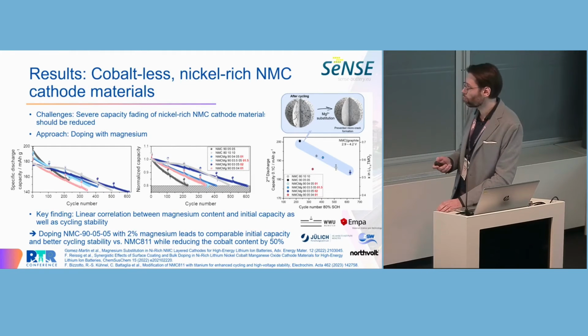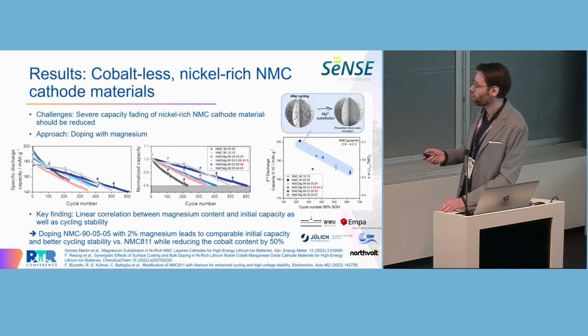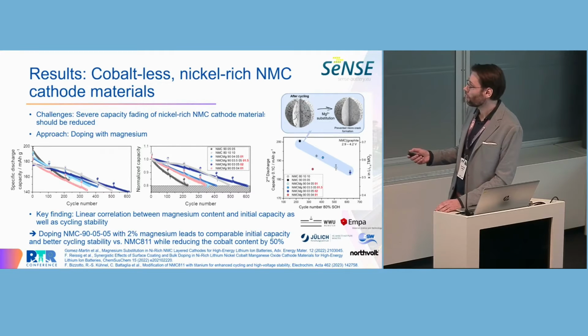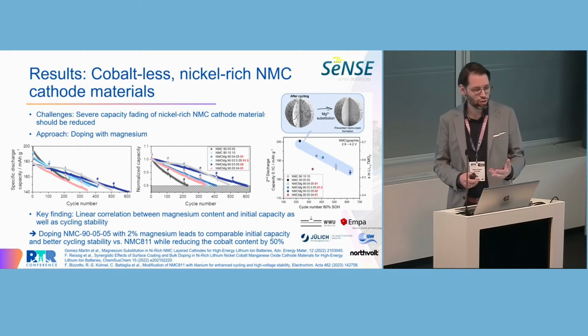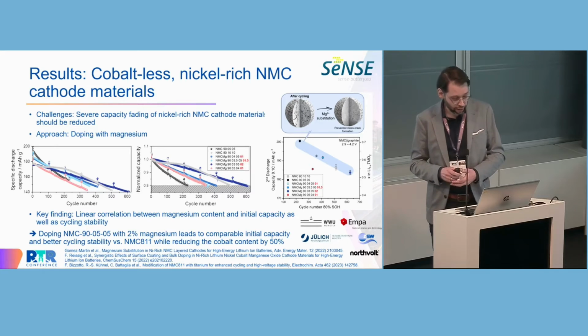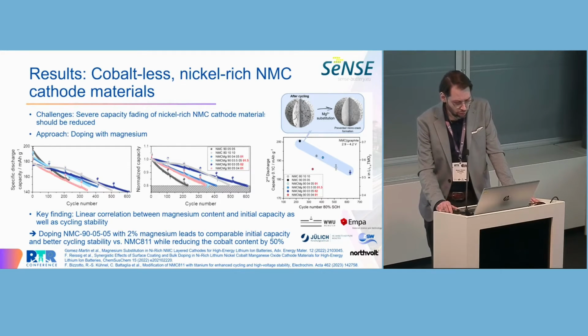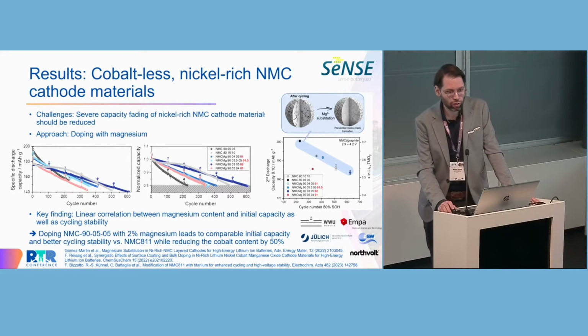Here I'm showing you an example of a substitution of some of the manganese by magnesium. In that way, we were able to achieve similar capacity as for NMC 811, but significantly lower cobalt content, 5% instead of 10%, by substituting 2% of the manganese by magnesium. Here in dark blue, you can see we achieved really nice cycling stability. In general, for this cell chemistry, you are rather limited by the anode side. The cathode material was then also scaled up by our project partner ZSW from Germany for the prototype cell. We produced around 20 kilograms of a layered oxide cathode material in the project.